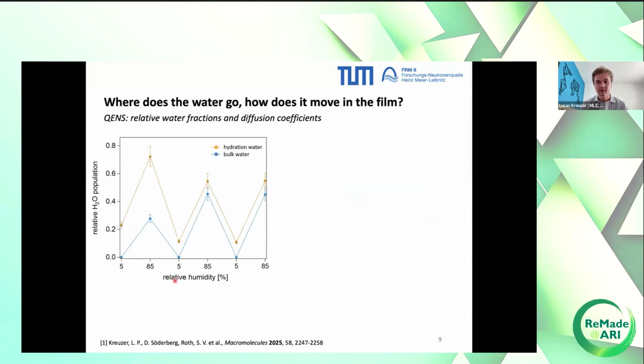And here you see two things. The first thing is that we always have more hydration water as compared to bulk water, even in the humid state. And I think this is a result of having these CNF, these fibrils, present in there. It really gives you a cellulose-based scaffold, which holds everything in place while still being reasonably flexible. And you don't have too big voids or pores that can be filled with water and then start to swell, because these films also don't swell. The CNF, everything holds in place. So there's actually not so much space for bulk water, and it's present in this film, yes, but to a relatively low amount. And most of the water is present here as hydration water close to the polymers.